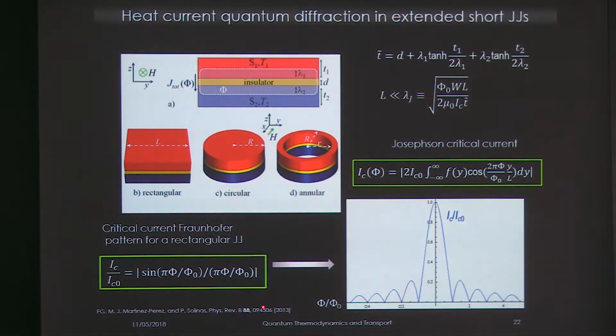Okay, and it happens in the same way. So if one solves the problem theoretically for an extended Josephson junction, depending on the geometry, rectangular, circular, round, or whatever, the electric critical current is just a Fourier transform of the critical current density along the y direction. Okay, and one can demonstrate that the phase-dependent part of the heat current has almost the same shape. Okay, so for a rectangular junction, there is a very well celebrated Fraunhofer pattern, the sine cardinal, where the minima appear at integral values, and then there is this fading. Okay, and so for heat it should be the same.